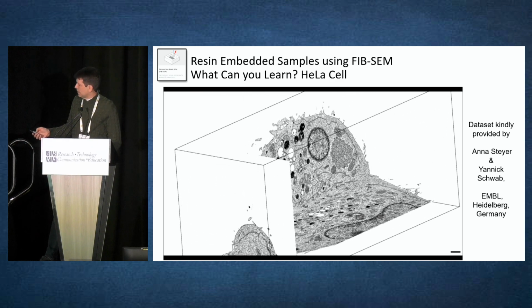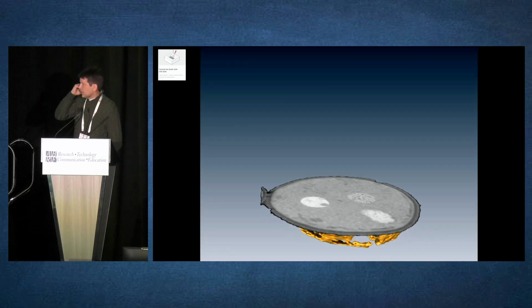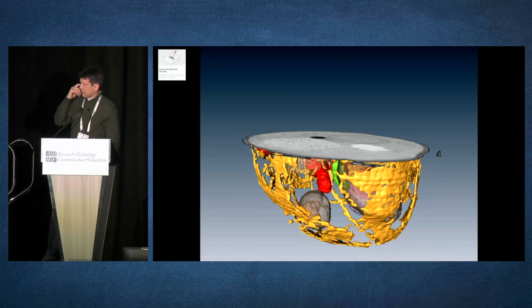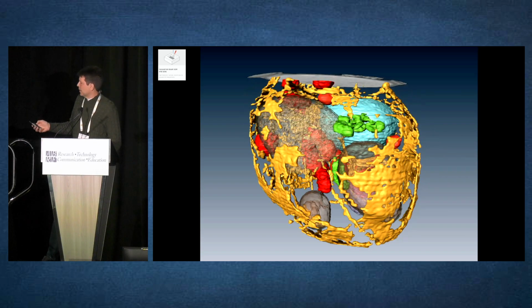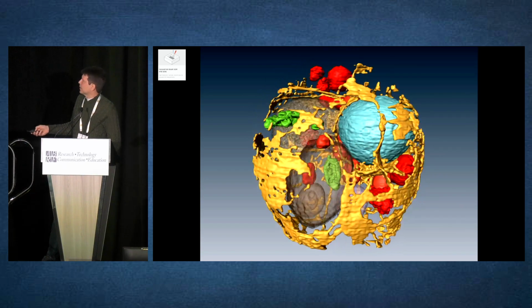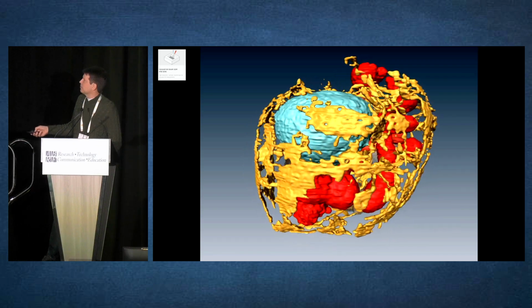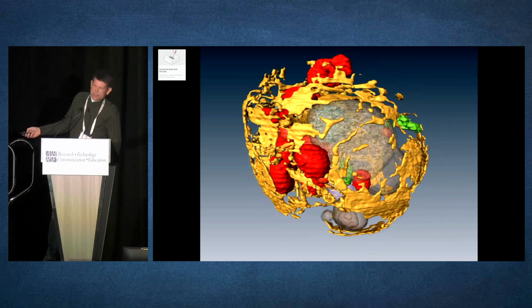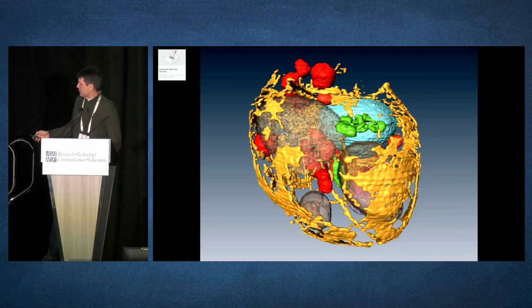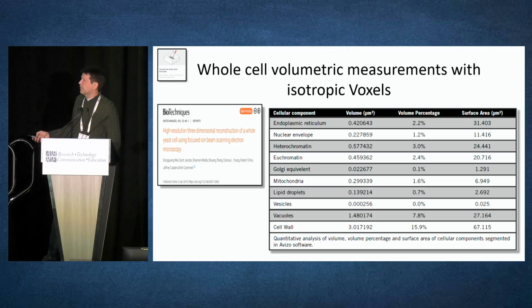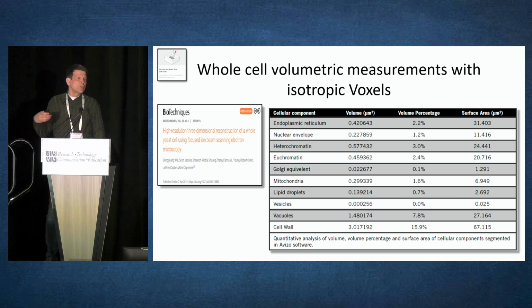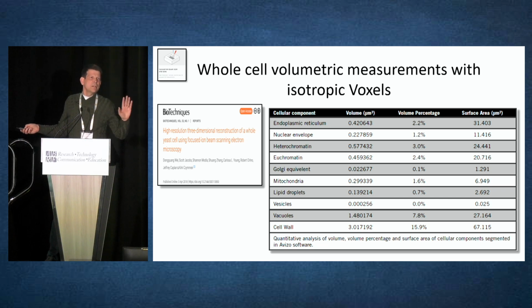Okay. I actually did some work with yeast. This is 3 nanometer isotropic. This was around 2012. So I labeled all the organelles inside of here. The endoplasmic reticulum is in yellow. The nucleus is in blue. The mitochondria, a lot of ER contact sites. But the cool thing about it is that this technique is quantifiable. So once you segment all these structures, you can start measuring them. So if you have a phenotype where you expect some effect that you want to measure, you can use this technique and take any kind of measurement you can from these three-dimensional structures.